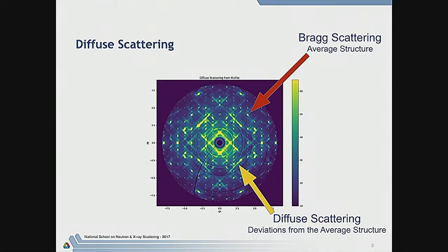So with X-rays, you see dynamic processes, but you also see static. With neutrons, in principle, you have the possibility of separating out the elastic scattering. That is S(Q, omega) where omega equals zero, and that is the T equals infinity correlation function. That is the static disorder in the material, again averaged over the crystal. So that's what diffuse scattering is.